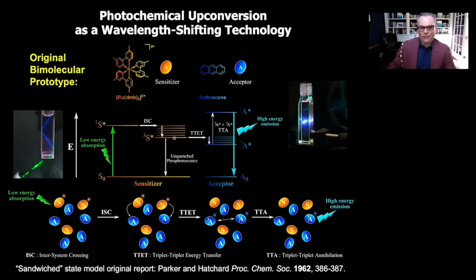Other than that, you'd like to have the ability to do fast energy transfer between the two chromophores, and you would like the triplet excited state of the acceptor to be really long-lived to give you the opportunity to engage in bimolecular energy transfer with other energized triplet molecules. If you put all of that together, what ultimately happens is that you can do this triplet-triplet annihilation, which is really two triplet excited states that collide and do Dexter energy transfer.